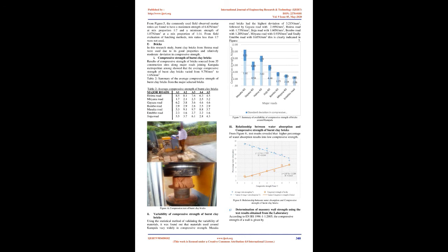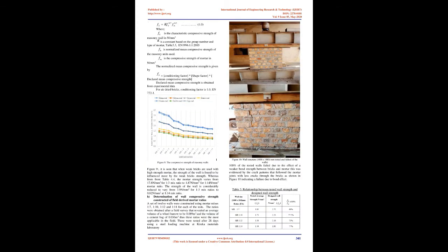Figure 5. Compressive strength of mortar cubes. From Figure 5, the commonly used field-observed mortar ratios are found to have a maximum strength of 6.82 N/mm2 at mix proportion 1:7 and a minimum strength of 1.87 N/mm2 at a mix proportion of 1:14. From field evaluation of batching methods, mix ratios less than 1:7 were not used.